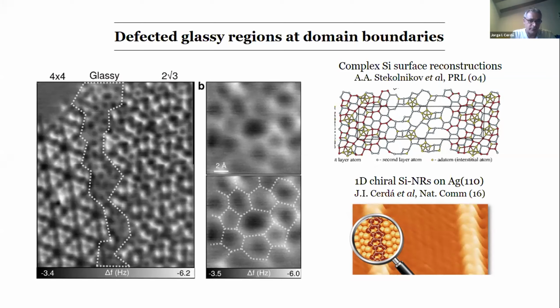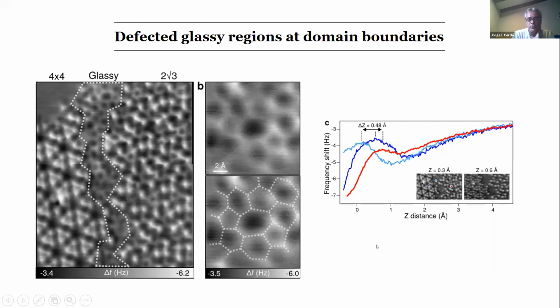I mean, this kind of distortion you can see in many graphene sheets, but it's hardly seen on silicon. Actually, you can see a heptamer here. You can have two pentagons, and pentagons in silicene are very difficult to see. They've been reported for some very complex silicon reconstructions like this one. Or recently, in work we did with a group at Autónoma, with Chema Rodriguez, where we found one-dimensional wires of silicon, solely made of pentagons. And I'll not be talking about that.